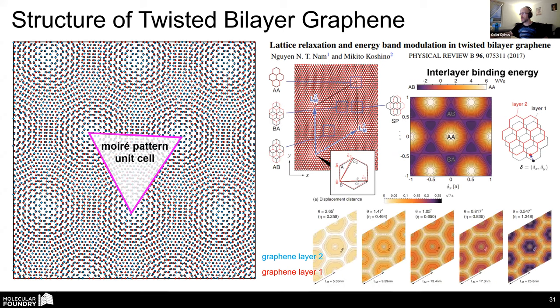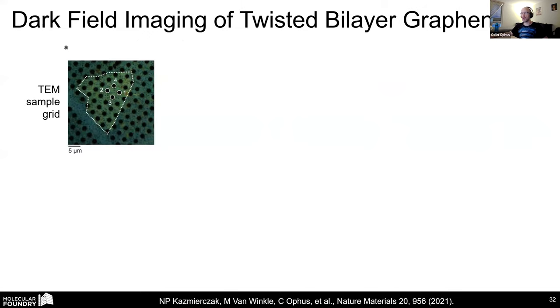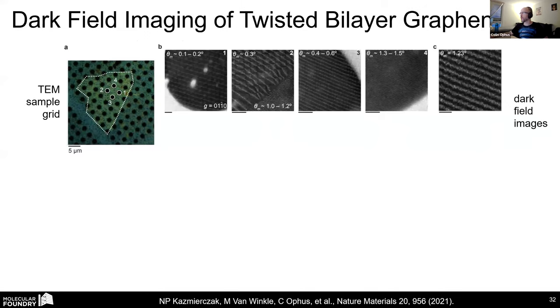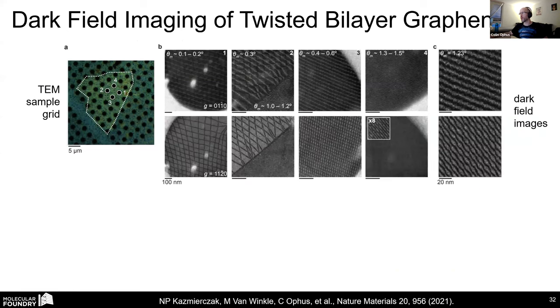And so a lot of authors predicted that there'd be a local relaxation where the material would try and maximize the AB stacking and minimize the AA or BB stacking. And so we set out to measure this experimentally. If you do a dark field TEM experiment on your sample grid here, this is just showing one of the dark field beams, I think 11 bar 20, you can already make out the moiré lattice.